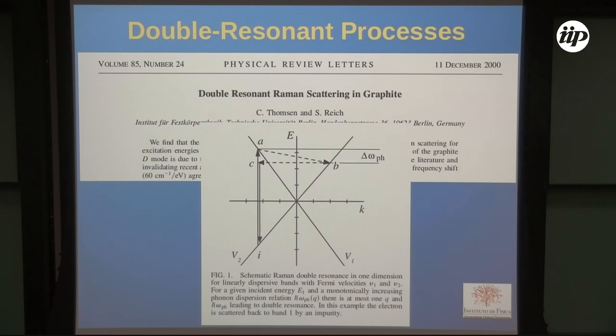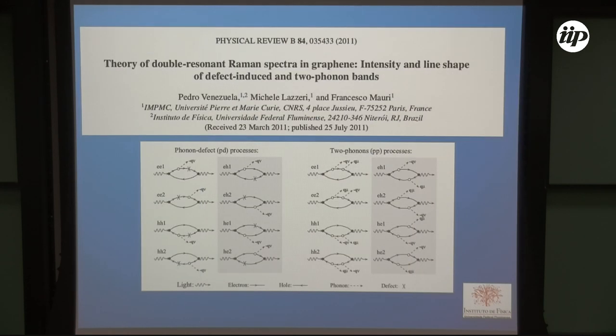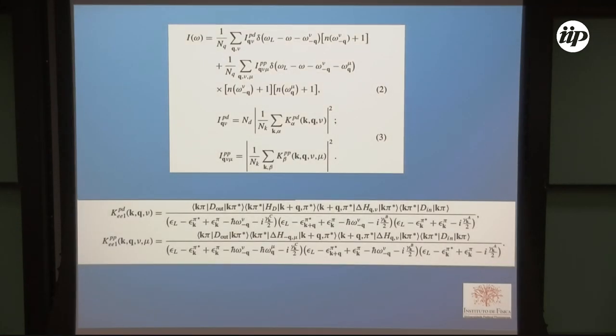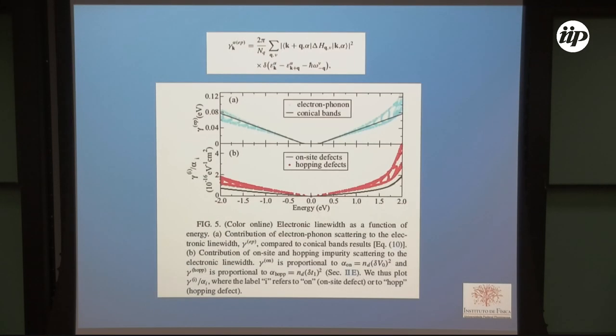So why is the inter-valley scattering larger than the intra-valley scattering? Because the electron phonon coupling close to the K point is larger than the electron phonon coupling close to the gamma point. Okay, we will come back to that later. But that is the short answer. Okay, so now we calculate that.